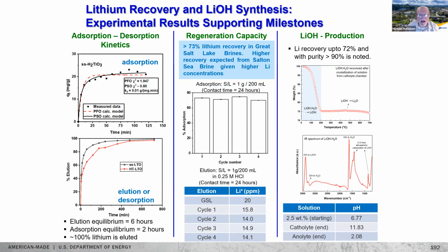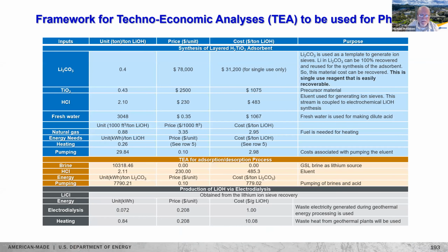Data on adsorption capacity and desorption elution efficiency are shown on the left, with first order and second order kinetic models fitted to them. Both solid state and hydrothermal methods of synthesis of the hydrogen titanium trioxide adsorbent have been tested. The middle chart shows that 70 to 80% recovery of lithium was obtained using the Great Salt Lake brines. The adsorbent was reused for 4 cycles. As noted earlier, we expect this endothermic recovery efficiency to improve at higher temperatures and higher lithium concentrations using Salton Sea geothermal brines.